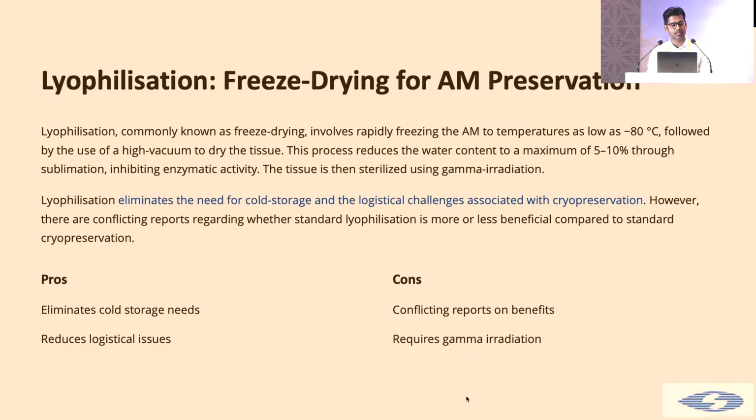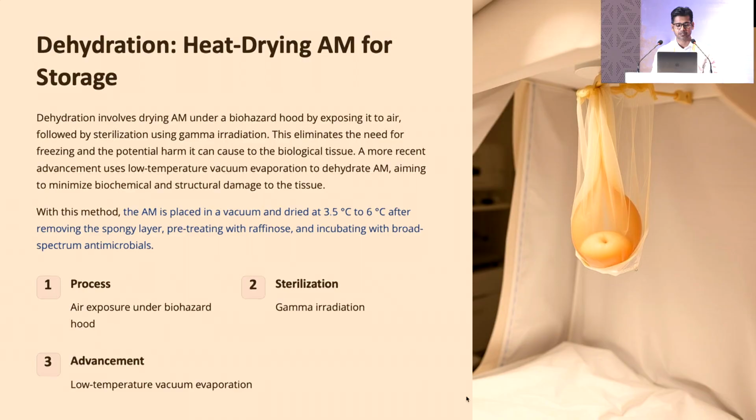The second one is lyophilization, which is freeze drying for amniotic membrane. It involves rapidly freezing it to -80 degrees Celsius, followed by the use of high vacuum to dry the tissue, and this eliminates the need for cold storage and logistical challenges associated with cryopreservation.